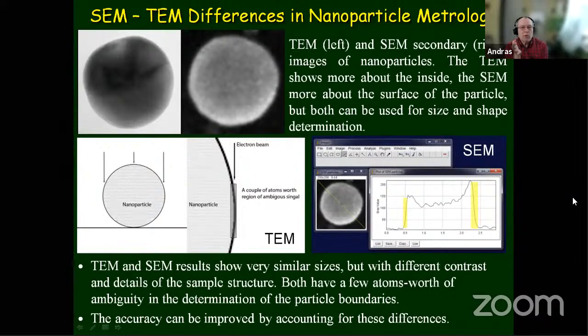And that's not feasible really, but both for TEM and SEM, there is that border region, which can easily be a couple of nanometers for a 30 or 10 nanometer size particle. That is a significant region of ambiguity to deal with. And the best way to do that is through modeling and simulation, when you can interpret the results that if it looks like this, then it must be that. So then the next slide, please.